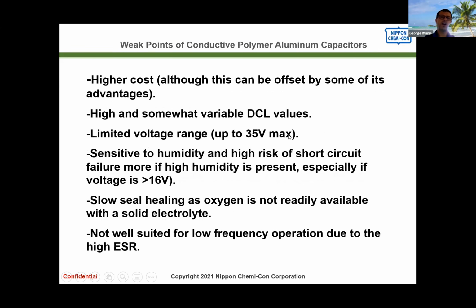Disadvantages: it has a higher cost, of course, but this higher cost is really an issue only if you try to replace one-to-one. So if you have a 10 by 10 millimeter size electrolytic and you're trying to put a 10 by 10 millimeter size polymer, of course the polymer is going to cost more. But generally speaking, you don't do that. You would replace 5 or 6 electrolytics or larger size electrolytics with one single polymer.